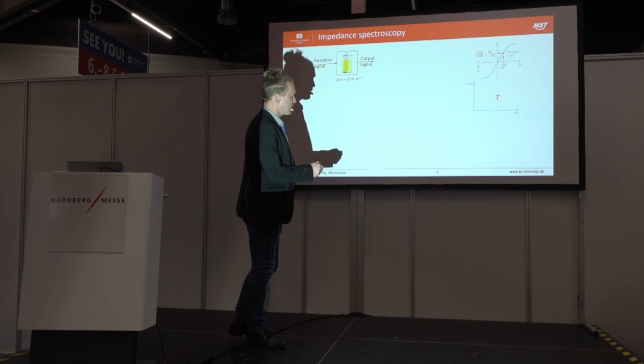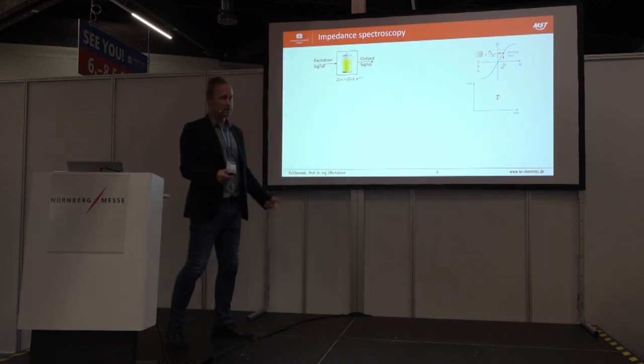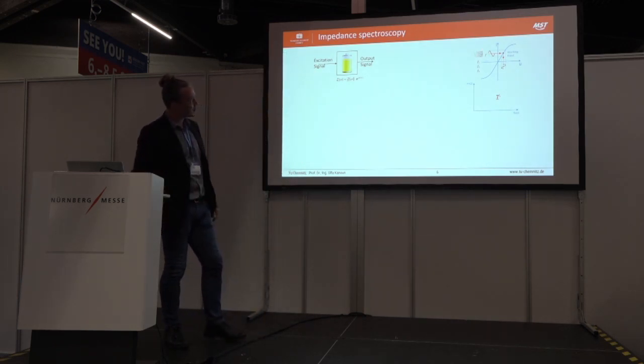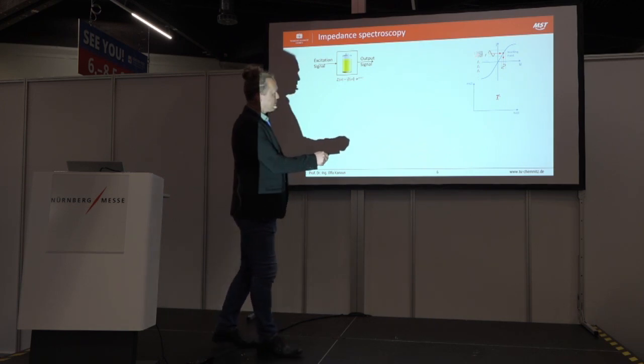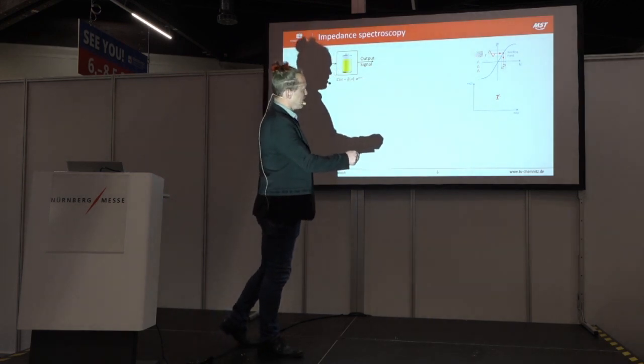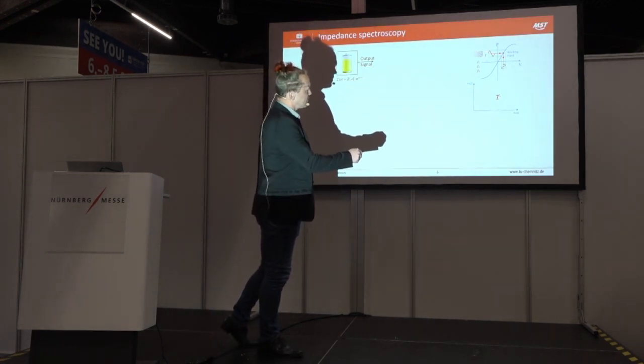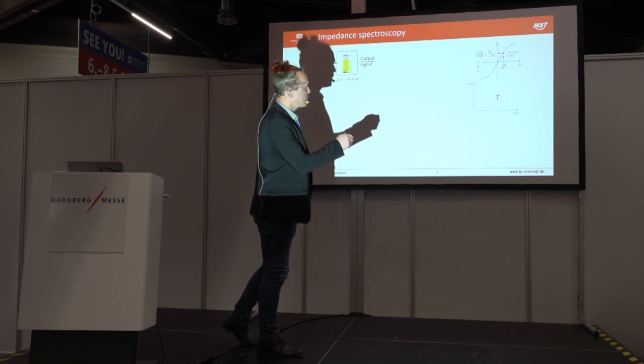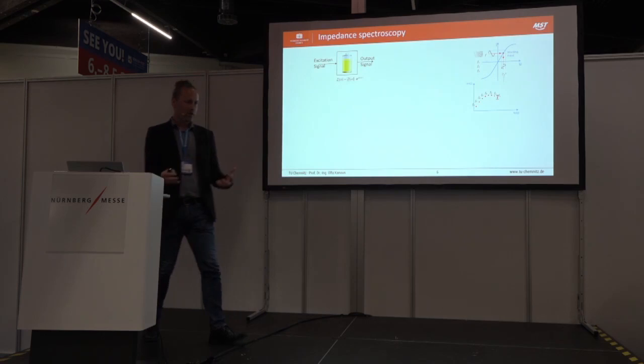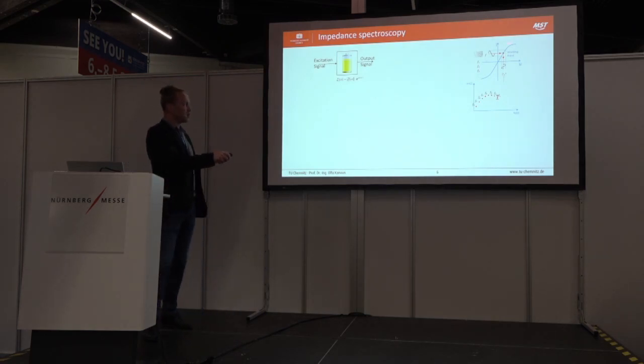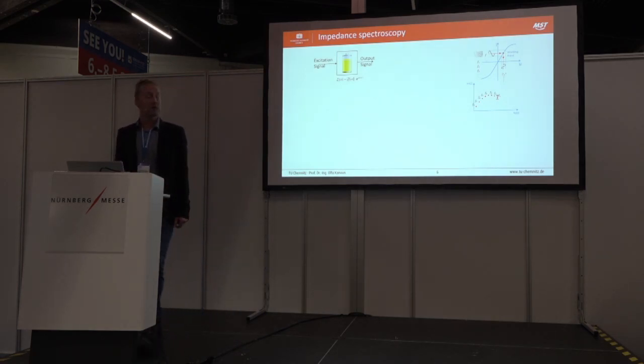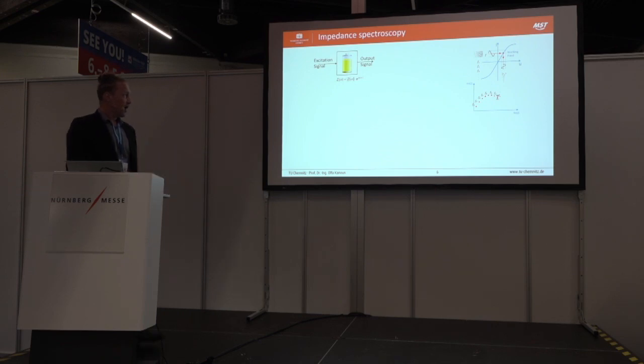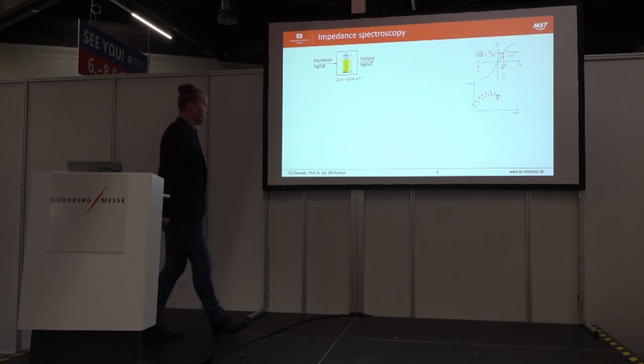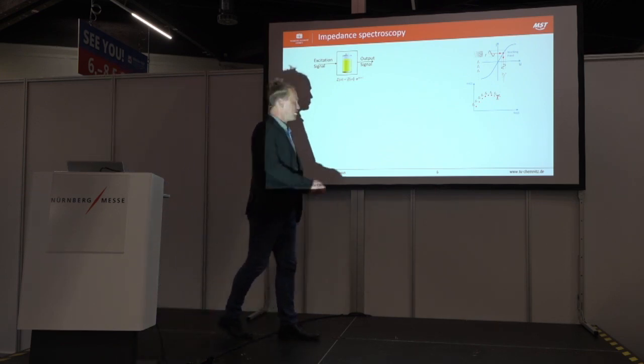You see here a so-called sweep from a low frequency to a higher frequency. We apply a sweep of excitation signal to this working point, and for sure we get also a certain response depending on the behavior of your system. And this becomes a little bit clearer further on.